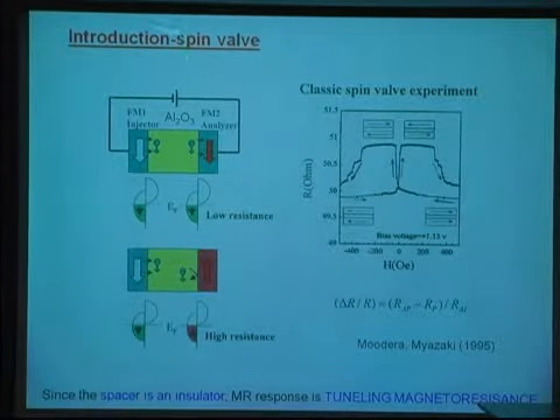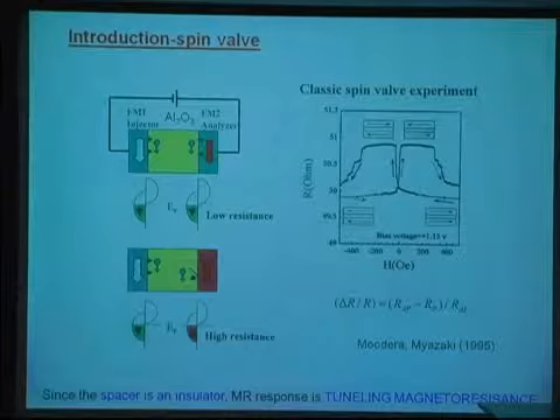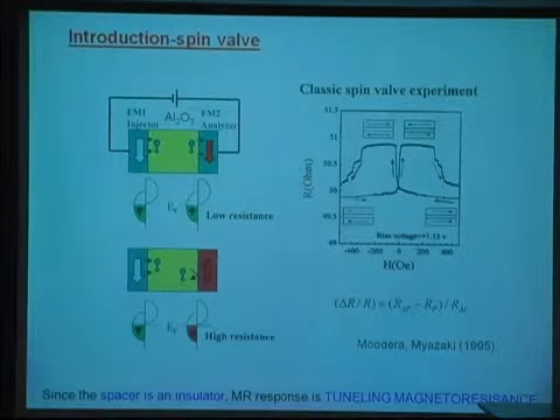Okay, the other example is tunneling magnetoresistance, in which we use aluminum oxide as a spacer. And you can see in this configuration, there is no concept of spin transport here. But you can see the magnetic responses are identical, because the principle for accepting or rejecting the injected electron spin is the same as in the giant magnetoresistance. So in this case, we call it tunneling magnetoresistance. This is not giant magnetoresistance. The spin-aligned carrier just tunnels through the insulator without any spin transport.